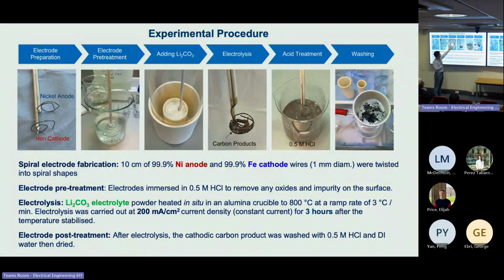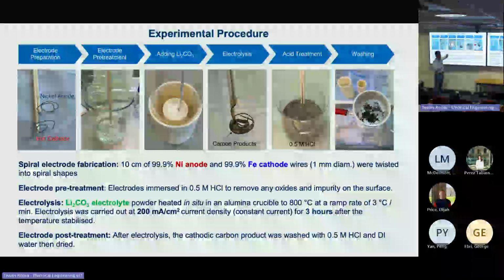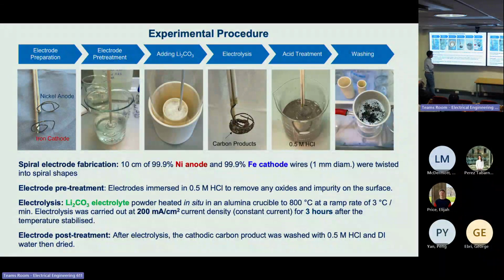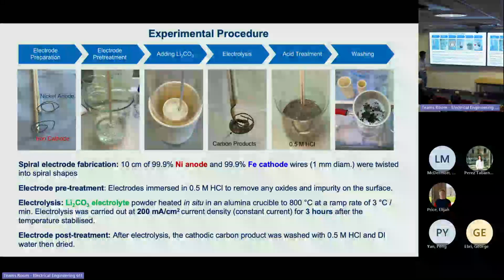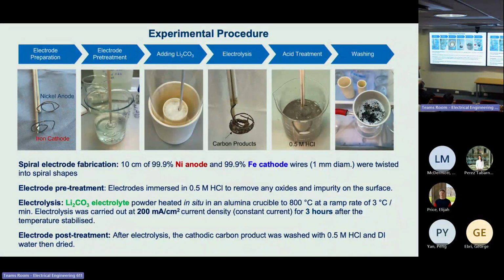We put the electrode into the central small crucible and bury it with lithium carbonate salt, 99.9% pure. And we put the whole thing into a furnace and heat up to 800 degrees at a ramping rate of 3 degrees per minute. Then we apply a voltage using the potentiostat between the two electrodes at a current density of 200 milliamps per square centimeter for 3 hours. And then we take out the electrodes. We can see some carbon products produced on the cathode, the bottom iron cathode. And then we use 0.5 molar hydrochloric acid again to wash the electrodes to remove the carbon.